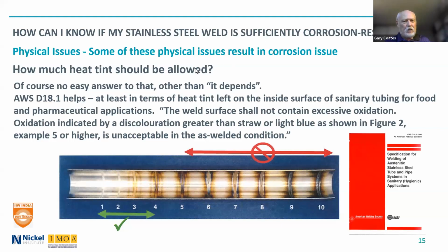Many years ago, we worked with AWS, the D18, to develop the D18.1 spec, and it was meant for the inside surface of sanitary tubing for food and pharmaceutical applications. They said you can't get the number 1 level, perfect, there. What heat tint is acceptable? They did different tests, and they said, well, up to this number 4 level, that is possible to obtain in a reasonable time period, at reasonable cost. So 4 and under generally is acceptable in that application. 5 and above to 10 is not acceptable. In other applications, you might accept a 5, for example, and this is assuming you don't do anything to remove that heat tint afterwards.